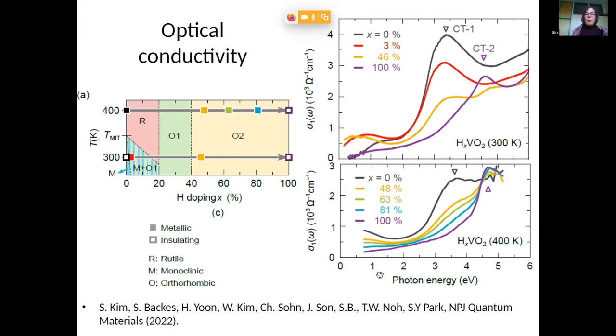And so here I'm referring actually to a collaboration with a Korean group of Noh and Soyun Kim. And for the theory part, Siyang Park and Stefan Backes. So what they did in the experiment was to measure, for example, optical conductivity. Once in the low temperature regime, when you start from the insulating phase here. So this is the black curve, pristine M1 phase. And when you dope it, as I said, 3% is already enough to induce some metallic states here.